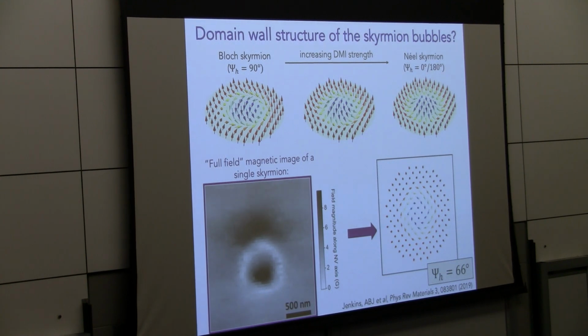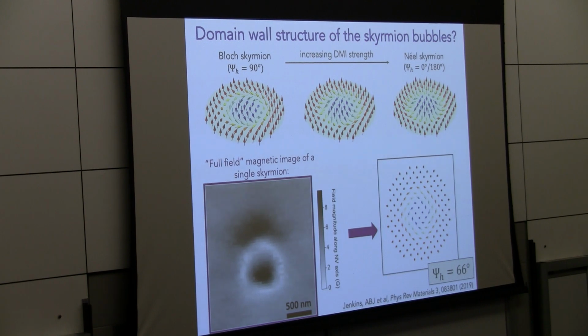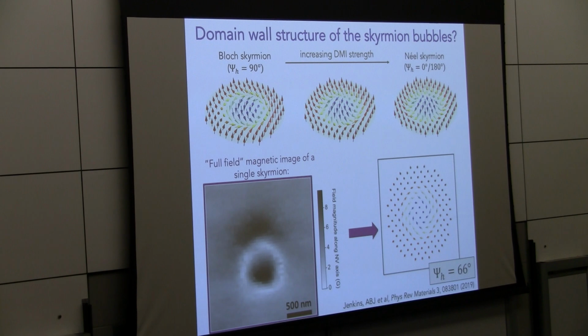Okay, and one expects these different types of domain walls to depend on the strength of the DMI compared to the exchange interaction. So for increasing DMI strength, one expects these Néel skyrmions, and whether one has a Néel skyrmion or a Bloch skyrmion drastically affects the way that it interacts with driving fields, for instance. And again, you can have anything in between. Using our NV imaging technique, we were able to infer what's called the helicity angle, and to actually image that angle of the skyrmion for these particular structures. So that was something neat that we could do.